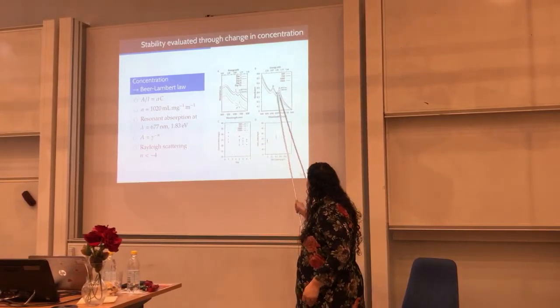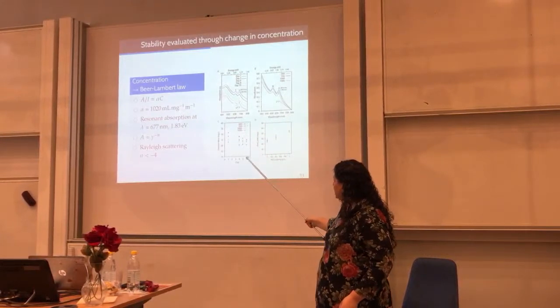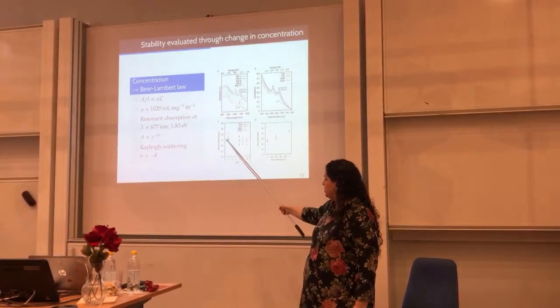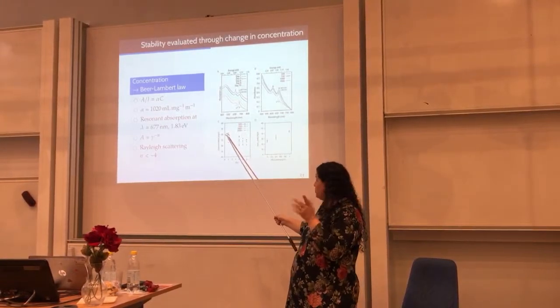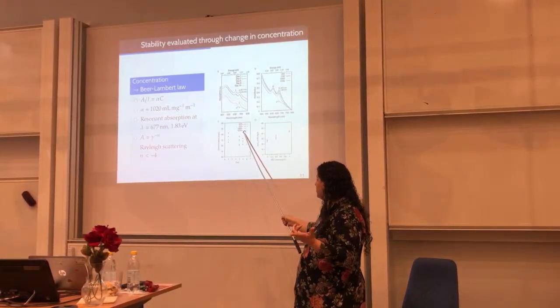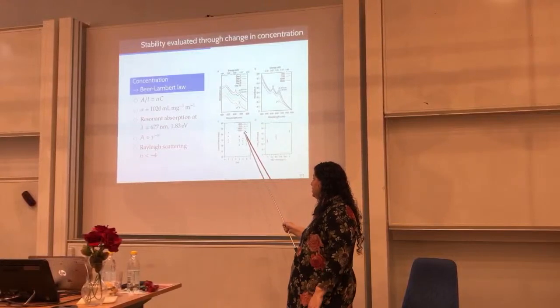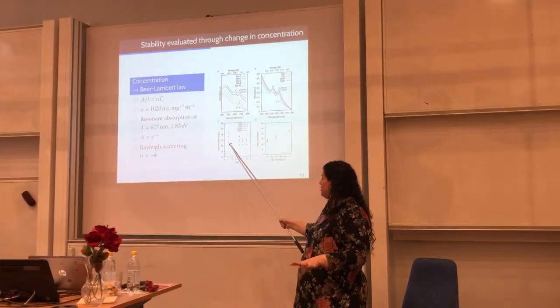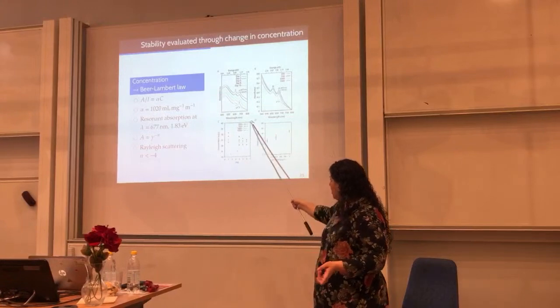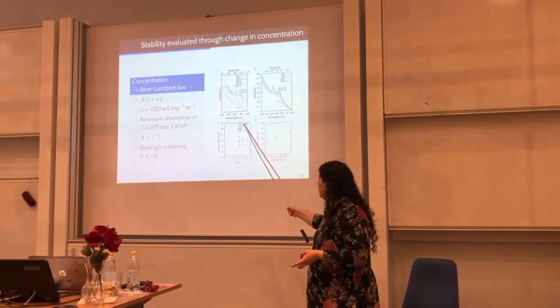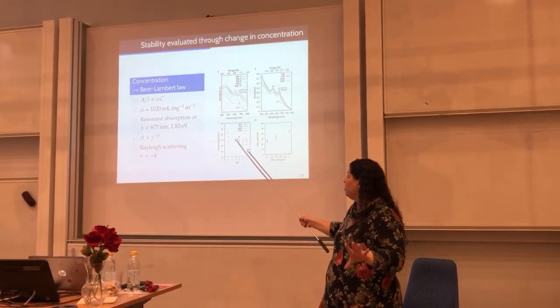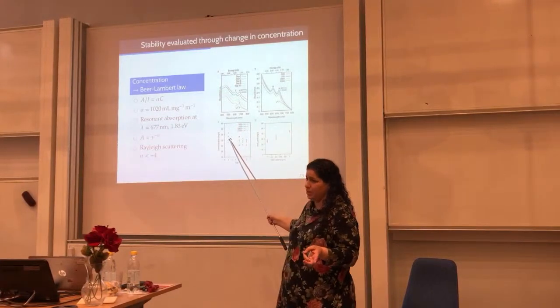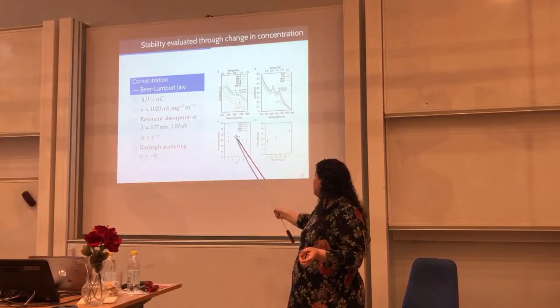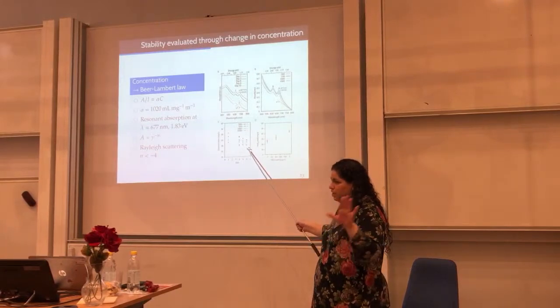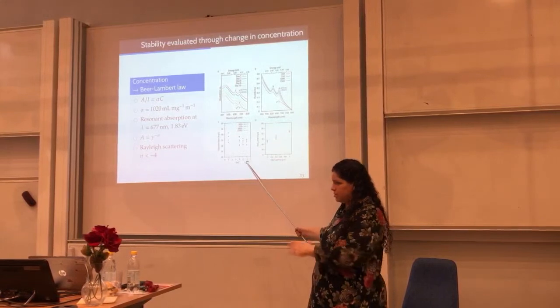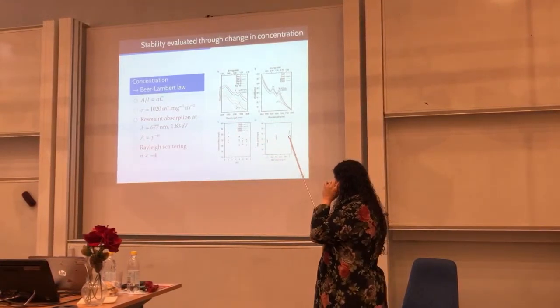Okay, then when I translate this result into concentration, I have these values here. So the concentration of my dispersions at 1,500, that's the lowest centrifugation rate that I had, was around 23 milligrams per liter. And at the lowest centrifugation speed, that means you're not sedimenting all the unexfoliated particles. Of course, you will have a much higher concentration. And this, of course, will change the longer these dispersions are standing on the bench, let's say.